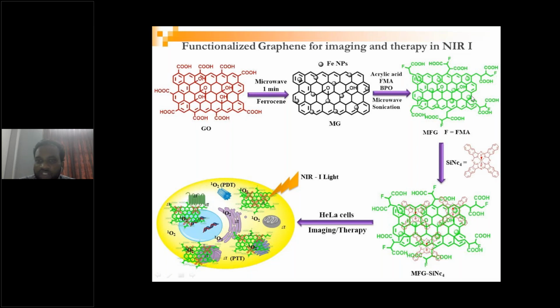But in order to check photodynamic therapy, we functionalized with SiNC, silicon naphthalocyanine, which is a singlet oxygen generator, which is able to generate singlet oxygen in the presence of light. So up to here, we adopted covalent chemistry, with covalent bonding to functionalize the molecules on top of the magnetic graphene. Whereas this is non-covalent chemistry.